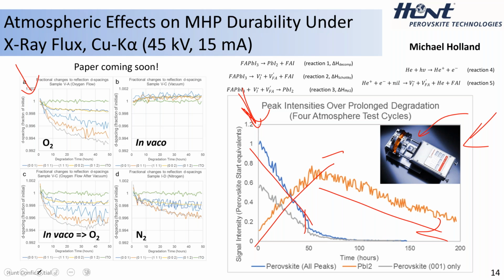So we tried it again here in vacuum, right? So we did an inert atmosphere, so just no atmosphere. So it's just under a vacuum, so no gaseous moieties floating in the air. And you can see there is no change in the d-spacing over the course of this 50-hour period from left to right.